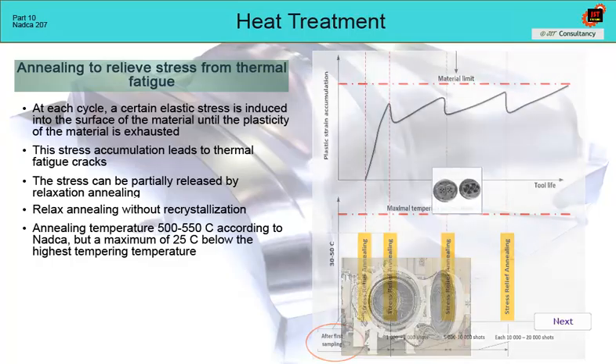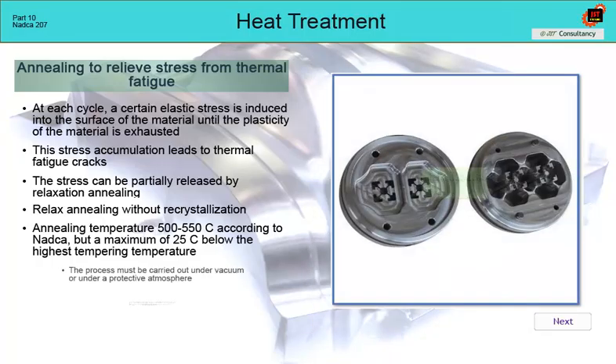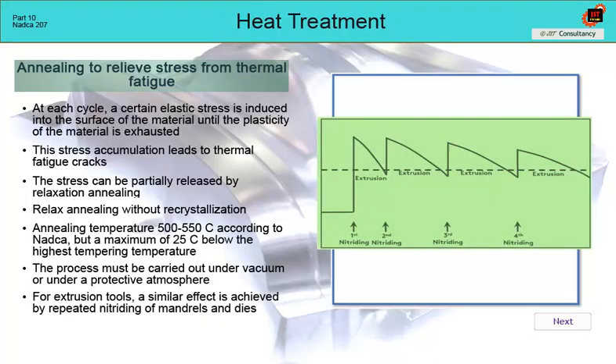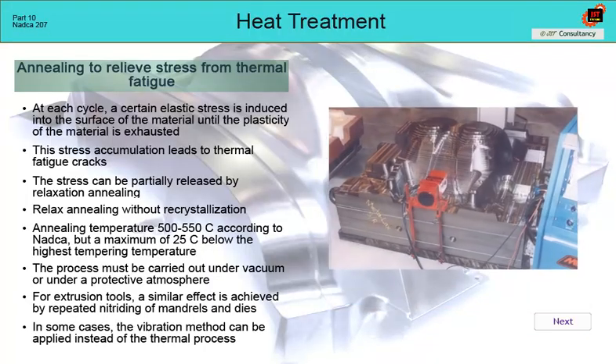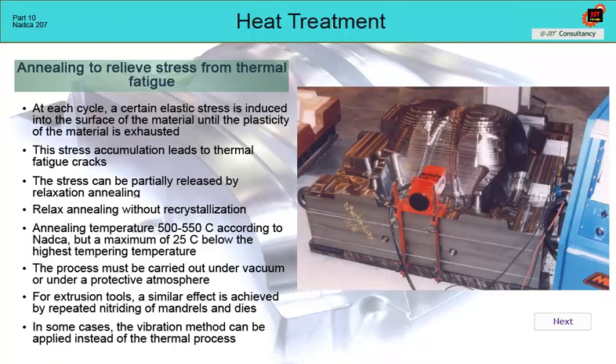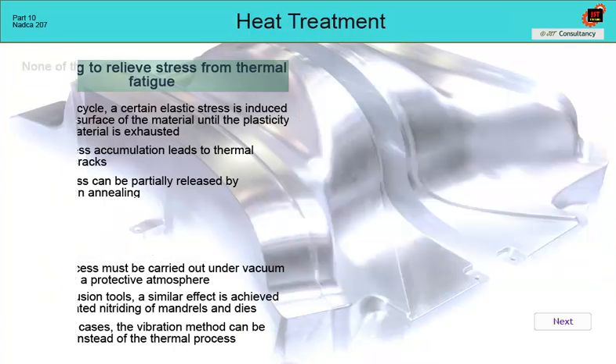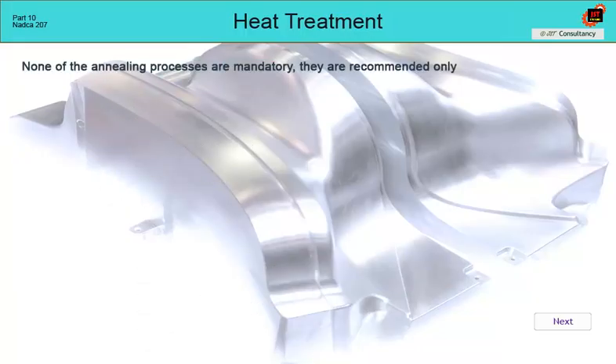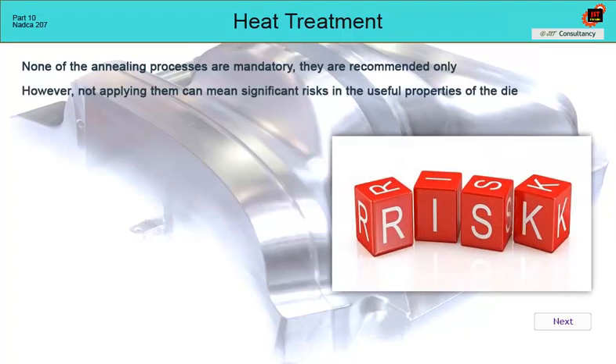A similar effect is achieved with tools for extrusion of aluminium profiles by repeated nitriding, according to the Nitrex prescription. In some cases, the vibratory method can be applied instead of the thermal process. None of the annealing processes are mandatory, they are recommended only. However, their omission can lead to a reduced service lifetime of the tool.